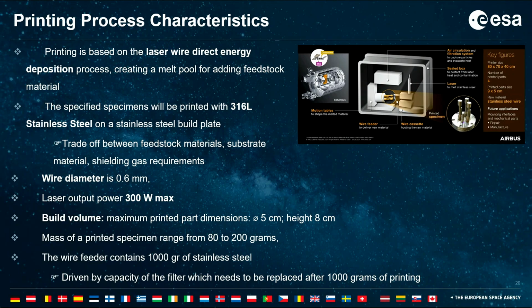What was driving the maximum mass in our cassette was actually the filter. As we said, with metals you have high temperature, evaporation, spatters, and you have a filter which collects all that so that it doesn't end up in the cabin of the ISS. And this filter gets clogged after about 1 kilogram of burning metal. So that drove the amount of material we had in the cassette.